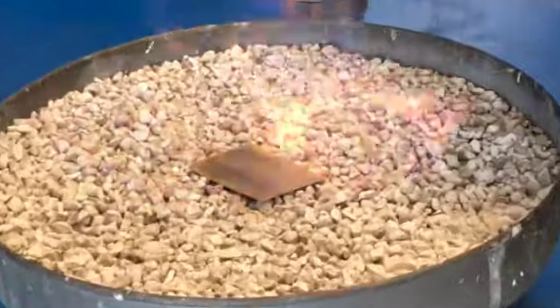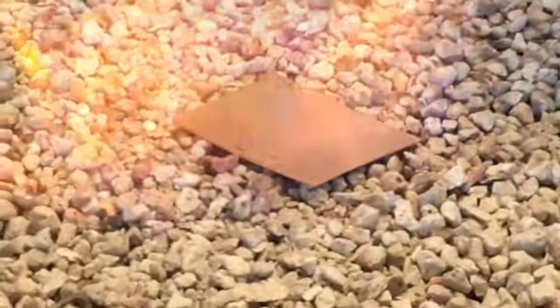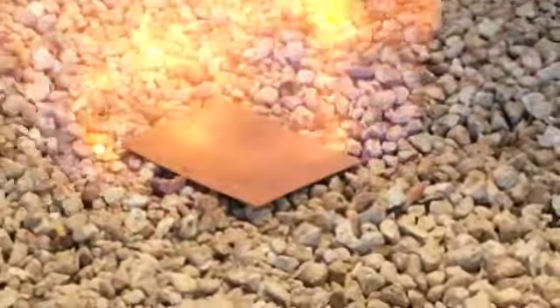As you heat your metal, your flux will go through several stages. First, the liquid water will evaporate. The flux will bubble up and then settle down, and it'll look like it's been coated in powdered sugar. As you continue to heat, the solids in the flux will begin to melt, and at first they'll look like a dirty sludge. And as you keep heating, they'll thin and go glassy. This glassy stage is referred to as being mature. Your yellow brass is annealed when the flux matures.